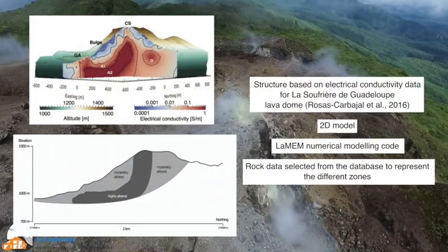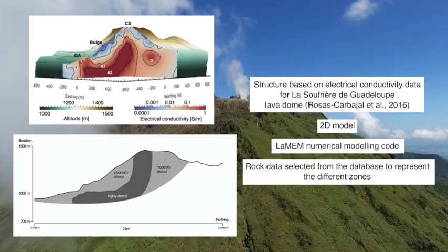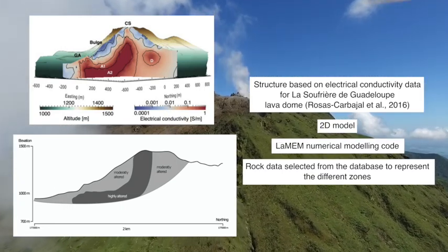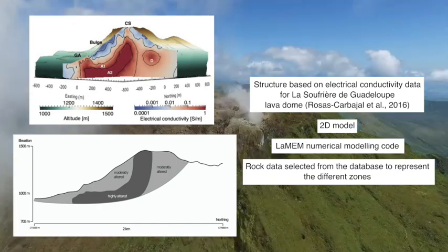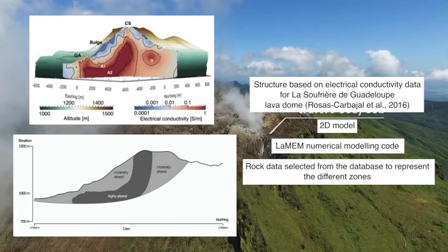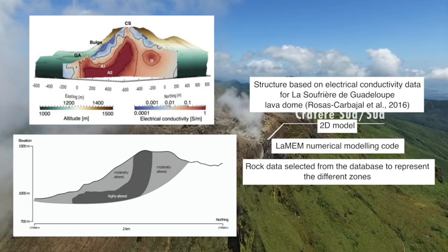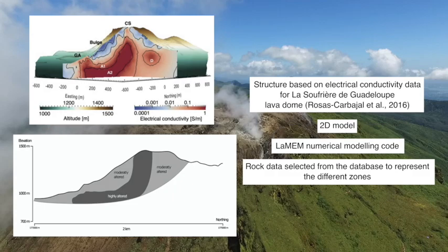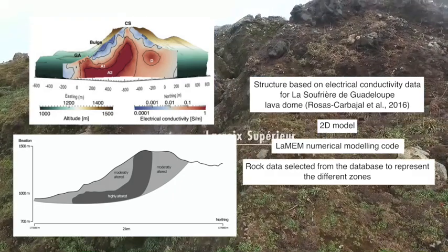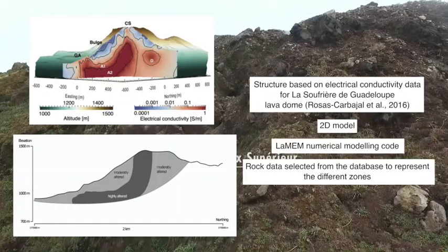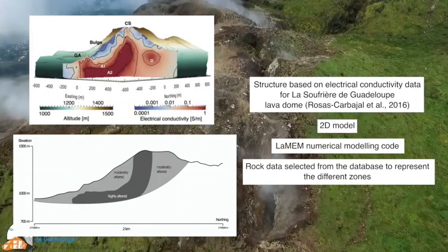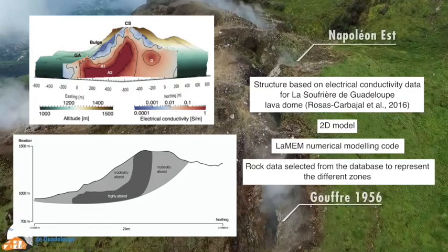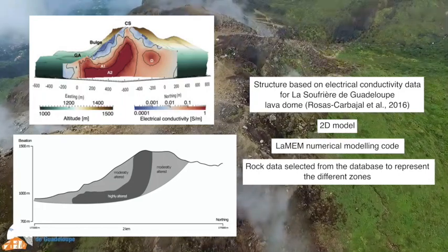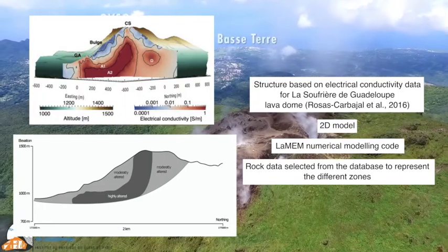We combined our laboratory data with geophysical data to perform 2D numerical flank stability modeling. We used recent electrical conductivity data, shown in the top image, to create our 2D cross-section, shown in the bottom image. Our simplified north-south cross-section contains 2 regions, a non-deformable region shown in white and a deformable region shown in grey. The deformable region was further split into 2 zones, a moderately altered zone shown in light grey and a highly altered zone shown in dark grey. These zones were characterized by different rock physical and mechanical properties as guided by our new laboratory data.